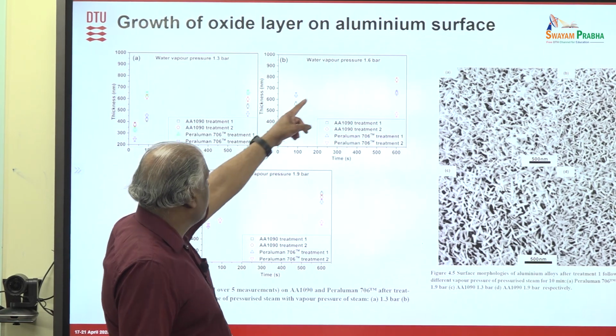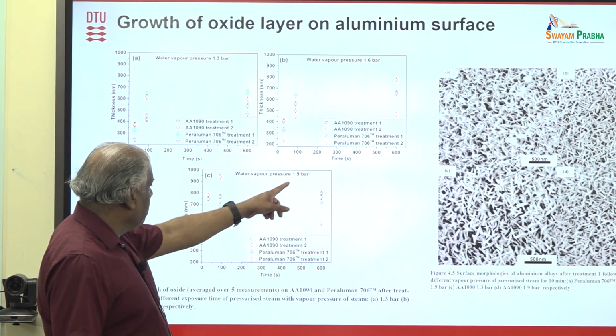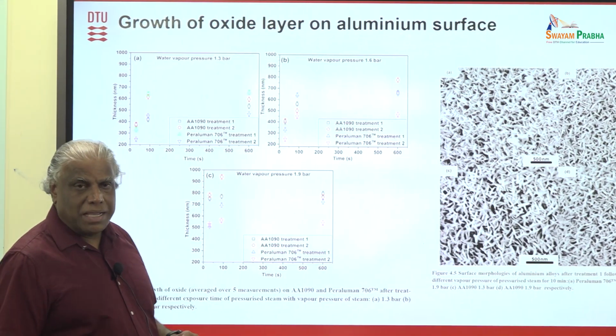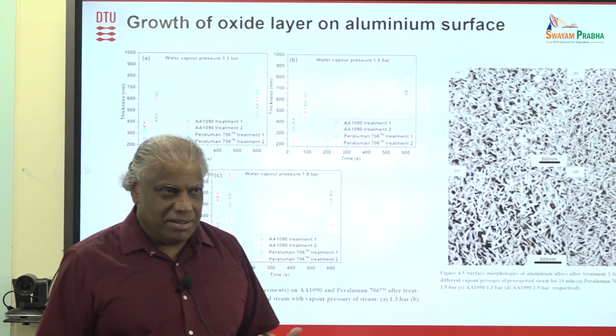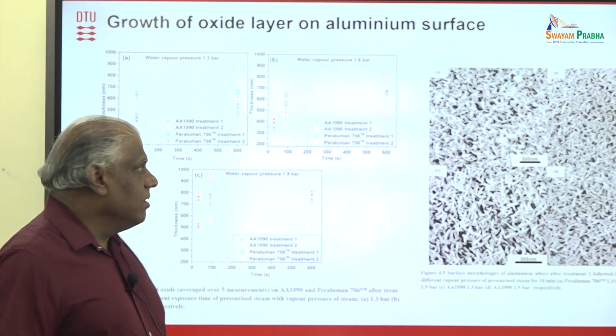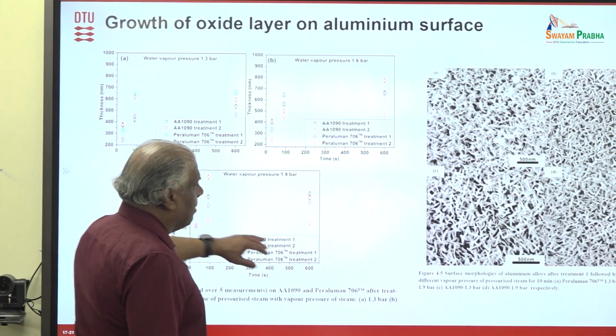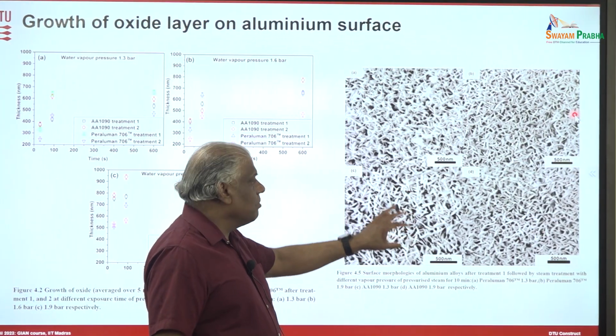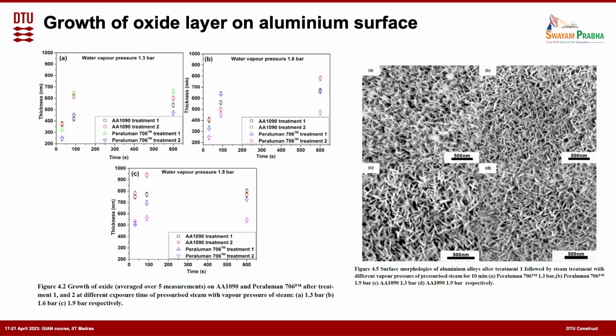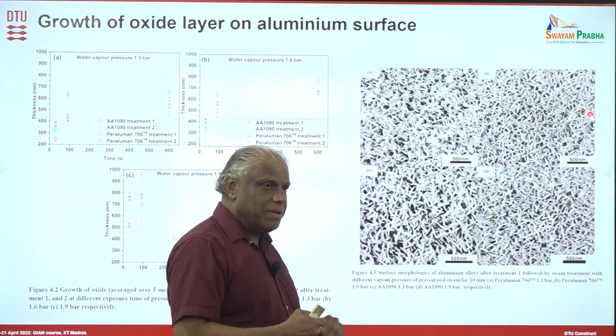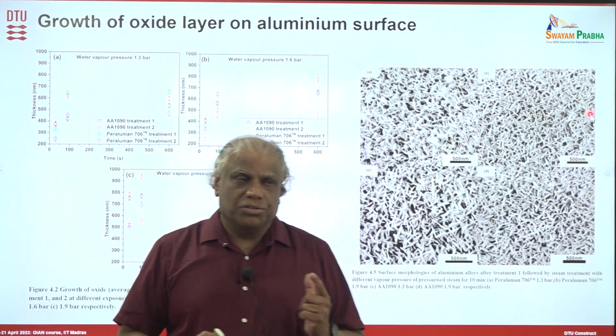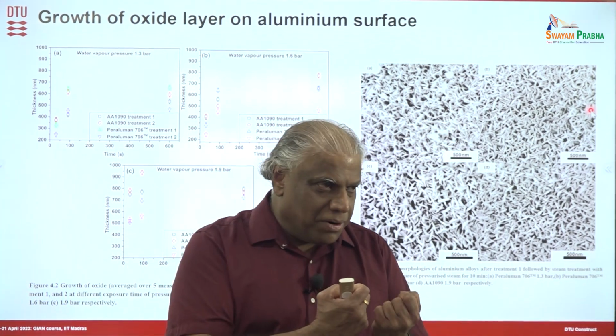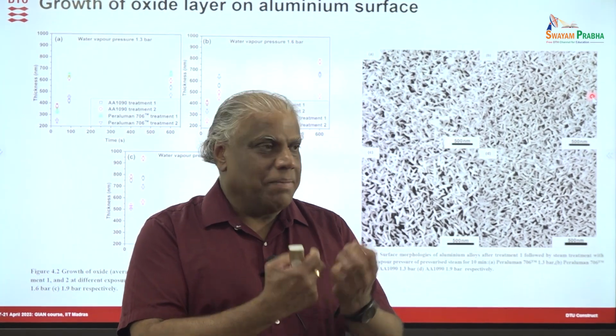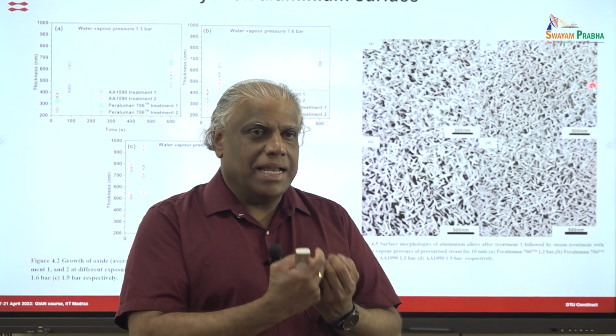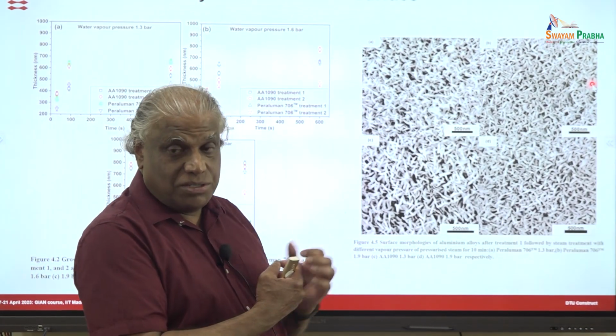With 1.3 bar, 600 nanometer; 1.6 bar is almost the same. With 1.9 bar, we can go up to 1 micrometer thickness. Thickness is not that important here. Even 600 nanometer or 300 nanometer is okay, but it forms the oxide and it also forms this rough structure. That's important. This nanoscale roughness is important because that will give a very good adhesion to the paint. Think that a paint is put on this. The paint adhesion is due to two factors. One is the chemical bonding. Another one is the mechanical locking. For mechanical locking, you need a rough surface. So this is good for that.